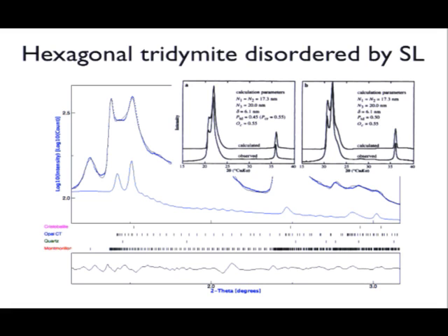Here, for example, if I take 10 times the cell, then you see some oscillation, depending on how small or bigger the crystallites are. If you want to avoid the oscillation, you just take a bigger cell so you approximate better, okay? But it takes longer time. So normally, depending on how big or small your crystallites are, you choose a supercell that smooths out the oscillation that is due to the fact we are using small spheres to model a rod, okay?